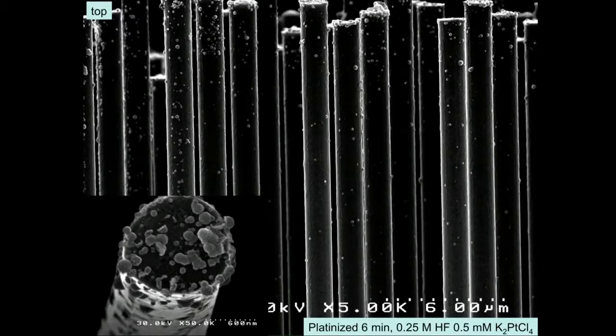Well, we can also take catalysts, because unfortunately the sun isn't a laser, as my graduate students are disappointed to learn, and doesn't make correlated photons making correlated electron hole pairs. And so if we're going to make chemical bonds, you need 2 electrons at least to make a chemical bond in the same place at the same time. And so we need catalysts to take those uncorrelated single electrons from those uncorrelated photons and use them to make and break chemical bonds. In our first demonstration, we used and sprinkled platinum as the catalyst for hydrogen evolution.